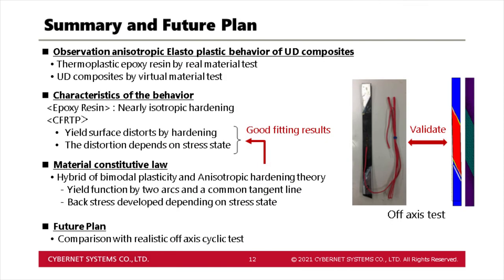I would like to summarize the main findings of this study and talk about a future plan. We investigated elastoplastic material behavior of UD composite. The material behavior of the resin was observed by real testing. Then, the material behavior of UD was observed by virtual material testing. As a result, it was confirmed that although the resin has isotropic hardening character, the yield surface of the UD composite tends to be distorted by hardening, depending on the stress state.